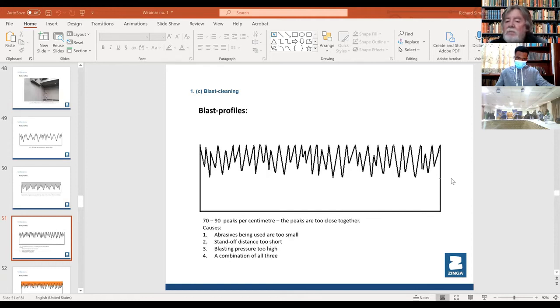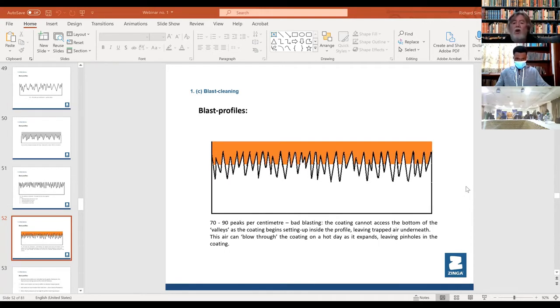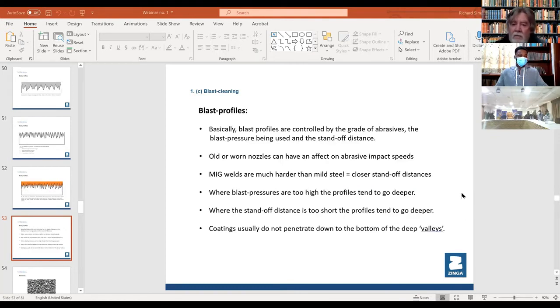This is one where somebody has put the blast pressure too high. He's come in and he's blasted it at about 7-8 bars of pressure, and the profile is the same depth, but your peak count is far too high. So there he's getting 70 to 90 peaks per centimeter instead of 45 to 60. And see what happens when you put a coating on, it goes halfway down, and because those blast profiles are so tight, your coating goes halfway down and starts drying from the heat of the sun, and it'll never go right down to the bottom of those profiles. So that again, you won't worry about this because you've had your blast spot set up. Your blasting has always been very, very good, but it's just to make you aware that sometimes some guy will do something wrong, and not in your team, but if you see this, you can identify it immediately. So we like to make you aware of this. So I like to teach all of our guys all these small points.